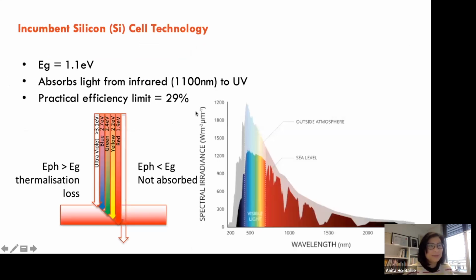Now, going back to silicon, if you remember, silicon is just a monoatom semiconductor or monoelement semiconductor, and it's got a band gap of 1.1 eV. So that's sort of equivalent to the infrared wavelength of 1100 nanometers. So it absorbs anything from infrared to UV, with photons that are above 1.1 eV. Anything below that will not be absorbed. But if you have photon energy of, say, 2 eV, the solar cell will get hot, so creating this thermalization loss. So the practical efficiency limit is only 29%, meaning it can only convert 29% of the energy in the solar spectrum into electrical energy.